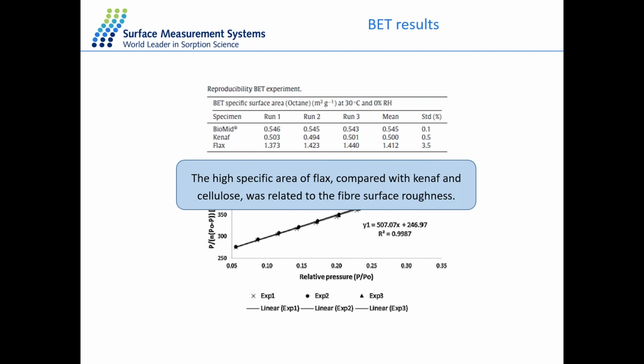So the specific surface area of the flax and the kenaf fibers can both be attributed to the surface roughness of these fibers, and as a result have a slightly larger BET surface area and slightly larger standard deviation.